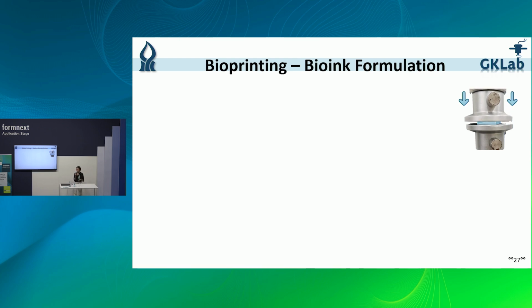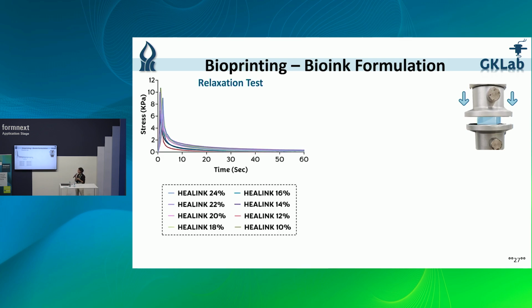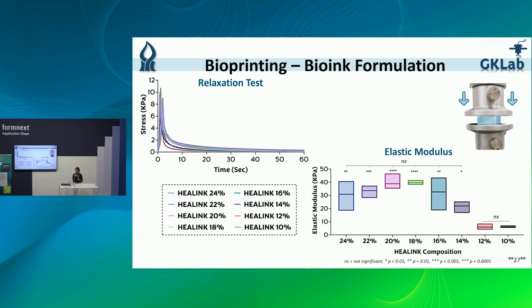So the first thing we did is to determine the composition of the bioink. So we tested several compositions of the HealInk bioink. The first test we did is a relaxation test, and we see that all of the compositions behaved quite similarly, with a rapid relaxation rate that is beneficial for cell growth. The next test that we did is to determine the elastic modulus of the different compositions. And around 20% we see an increase in the elastic modulus, meaning this hydrogel is stiffer and more stable. And therefore we chose that as our ideal composition.